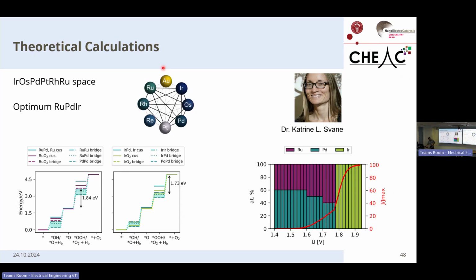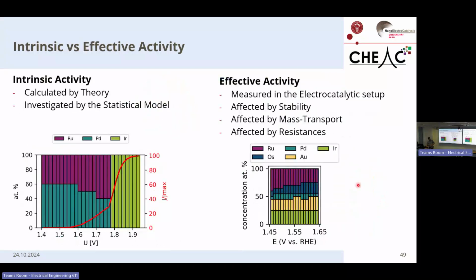And she observes that ruthenium and palladium have a synergetic effect. So the optimal catalytic sites are either a combination of ruthenium and palladium or pure iridium. But she cannot explain why we have gold and osmium incorporated into our system. So for this, to understand it, I would like to introduce you to two new concepts, and that's the difference between the intrinsic activity and the effective activity.